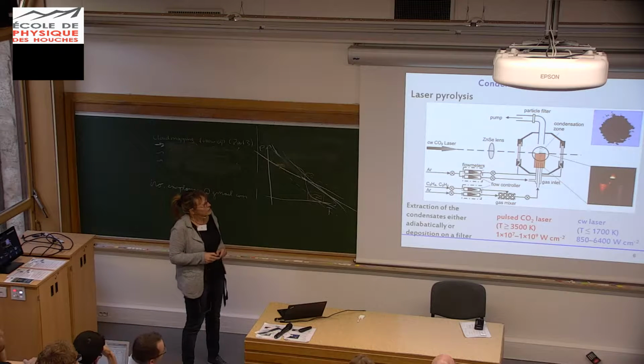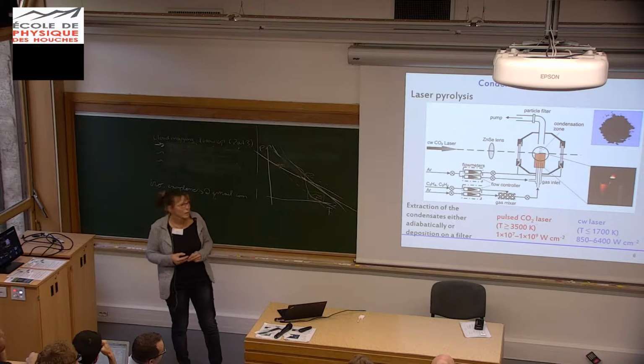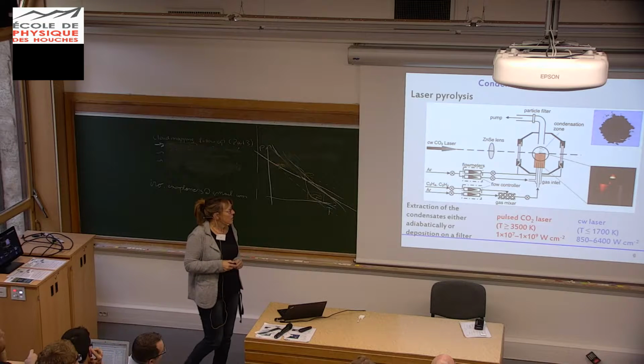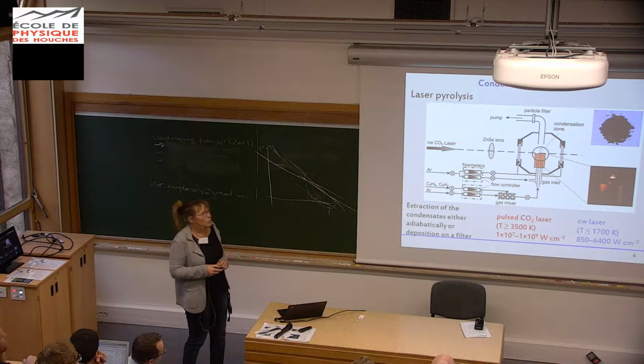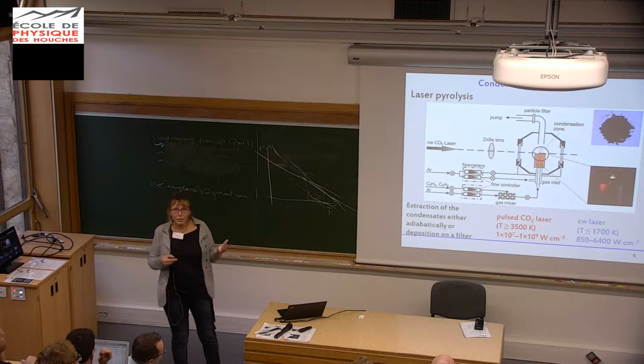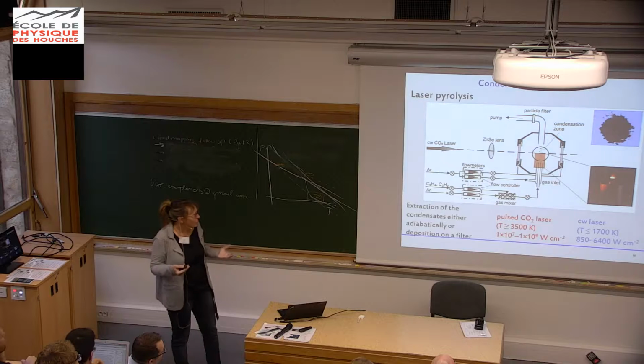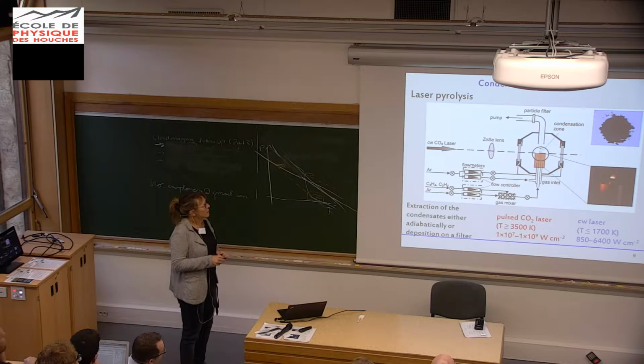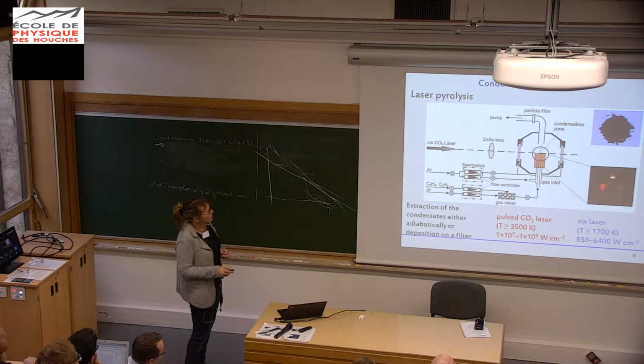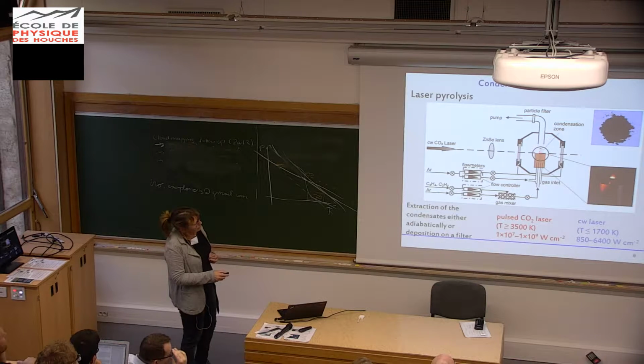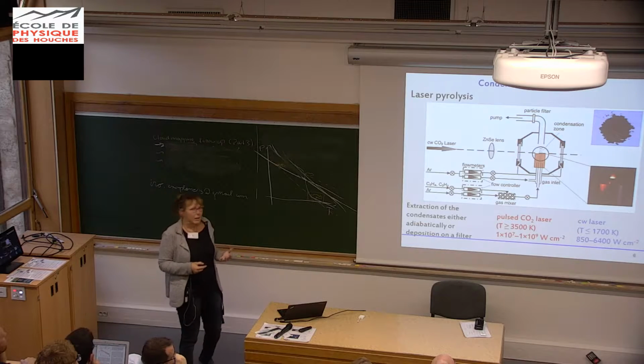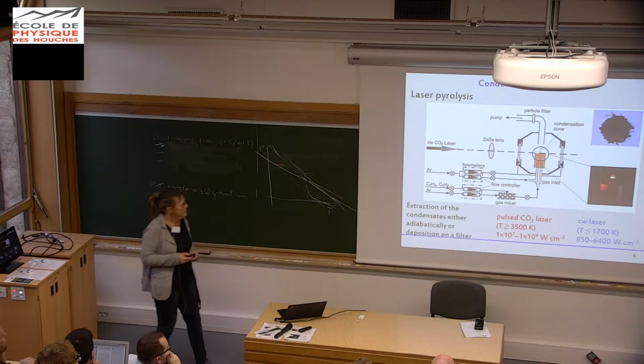The characteristic of laser pyrolysis is that you start with gaseous precursors. For example, if you produce carbonaceous condensates, you start with hydrocarbons like acetylene, ethylene, benzene, or you can also use methane. The gases are introduced into the chamber through the inner tube, and they are confined by a so-called confinement or quenching gas, normally a rare gas, argon or helium in most cases.